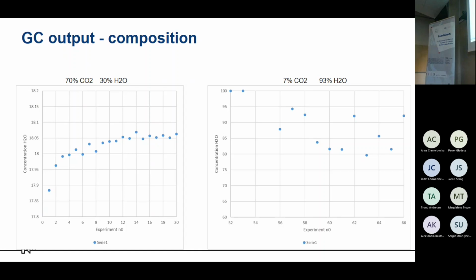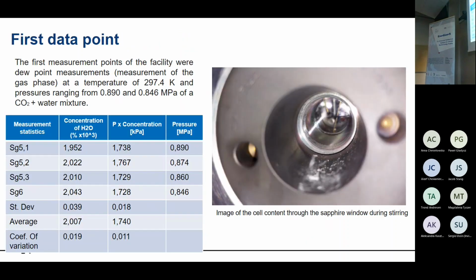The settings of the GC are very well adjusted, but for the 7% of CO2, the results are very different, from 95% of water to 80%. So it means that we potentially have condensation in the system, or the GC is not calibrated very well for this mixture. So it is important to have stable results. And we generated the first data point.